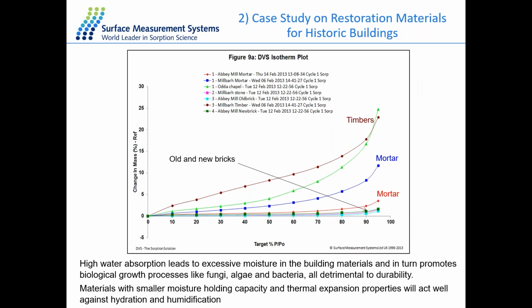So the water sorption properties are very useful indicators of durability because high water uptake will cause problems in the building, like the growth of bacteria and reduced thermal insulation. So it's very important to choose materials that have low water sorption capacity and also high strength. From the DVS data here, we can predict that the new and old brick samples and also the stone sample are more suitable for this kind of restoration work for historic buildings, with better strength and low water uptake capacity. So this is a study on the restoration materials where we measure the water uptake of the samples.